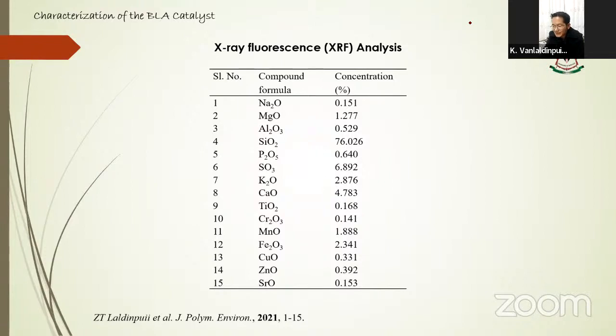So from this data, we can see that BLA was found to contain silica as the major component. This is silica, SiO2. The concentration is very high. It is 76%. That is the major component of bamboo leaf ash. Then, apart from that, several other metal oxides, such as potassium oxide, calcium oxide, sulfur trioxide, etc., were also present in varying amounts.